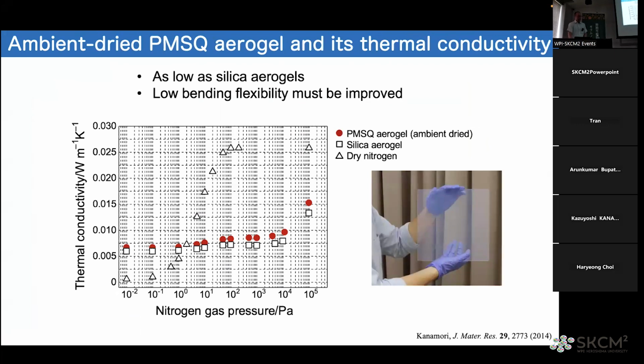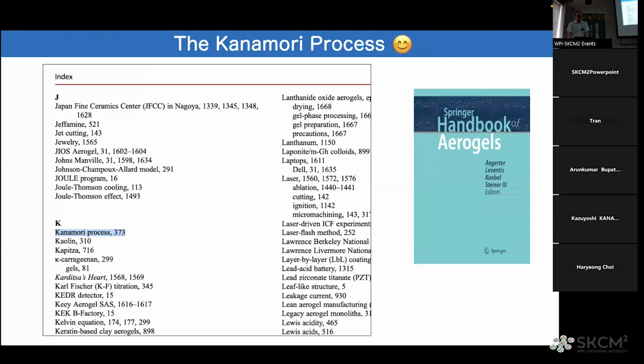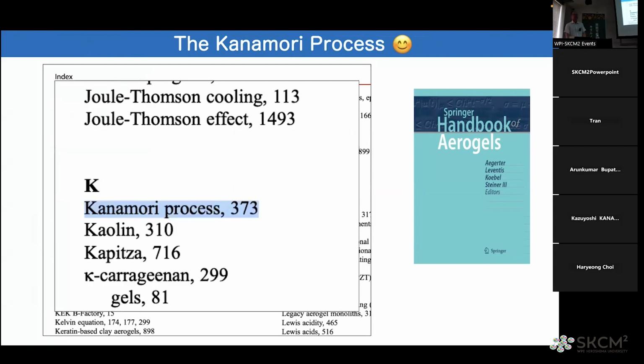After drying, we compared the thermal conductivity of our aerogel, and I won't go into detail, but we found that the thermal conductivity is almost the same as the standard silica aerogels. They have low enough thermal conductivity. And now we can prepare a 30 centimeter square panel by ambient pressure drying. In the Springer Handbook of Aerogels, in the index, you can see this is now called the Kanamori process. Please remember.